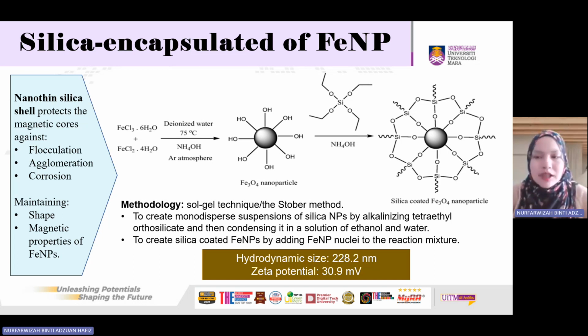In terms of its zeta potential, the silica-coated iron oxide nanoparticle has the smallest particle size, which is about 200 nanometers, and moderate colloidal stability of about 30 millivolts. This shows that silica-coated iron oxide nanoparticle has a moderate stability that reduces the agglomeration issue compared to the uncoated iron oxide nanoparticle as discussed earlier.